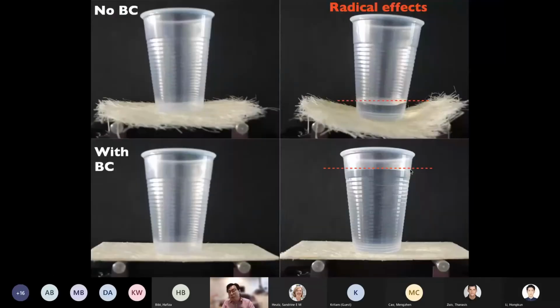Now, to demonstrate that without bacterial cellulose is not good, there's a picture here with an empty plastic cup. And we did it in a simple 3-point bending demonstration. So this is your loose sisal fibers. We just press them together with just a little bit of water in there. The whole thing flexes again because it doesn't have any rigidity associated with the final structure. With 10% bacterial cellulose, without water, again, nothing moves. But when you add it all the way up to 80% of the plastic cup, it still doesn't bulge at all. This is 170 grams.